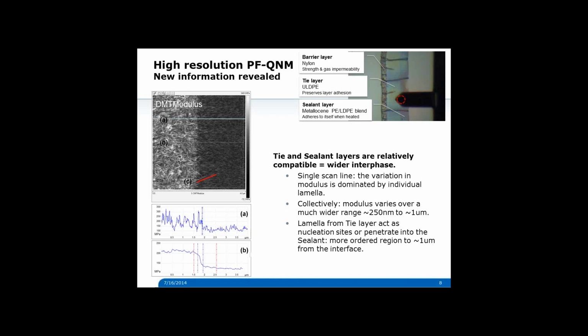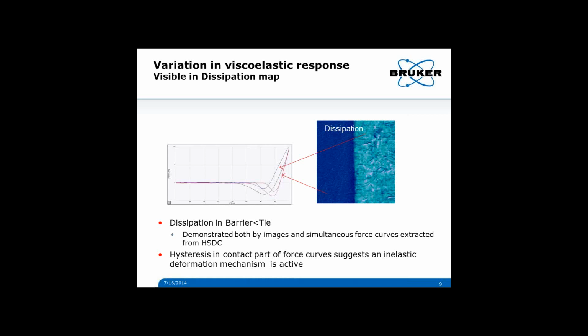Now, if I look at the actual force curves in these two different layers, the barrier and tie layers, you can see that there's a lot more hysteresis in the part that's in the tie layer. And that actually shows up in our dissipation map, because what it's doing is it calculates out the area between the approach and retract curves. And sometimes this is dominated by adhesion, but not so in this case, because the adhesion is roughly the same for these two. It's just the tie layer has more hysteresis.